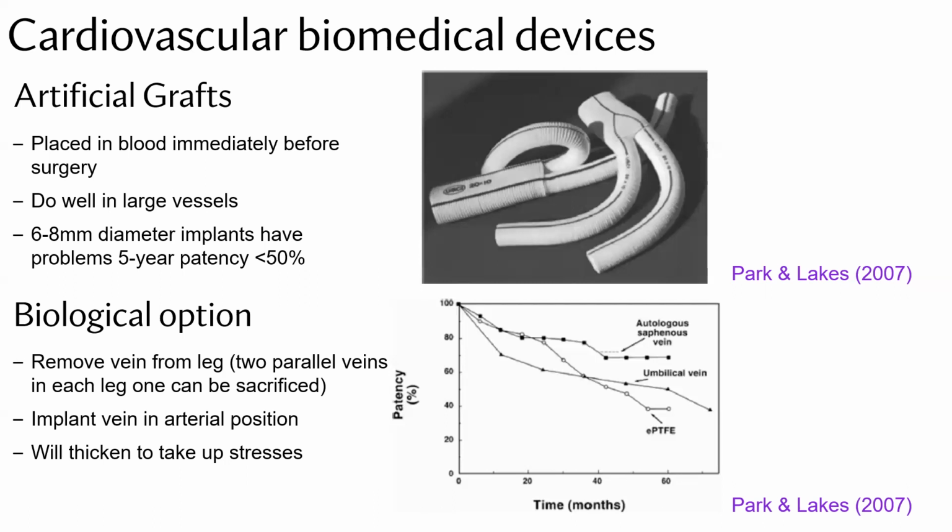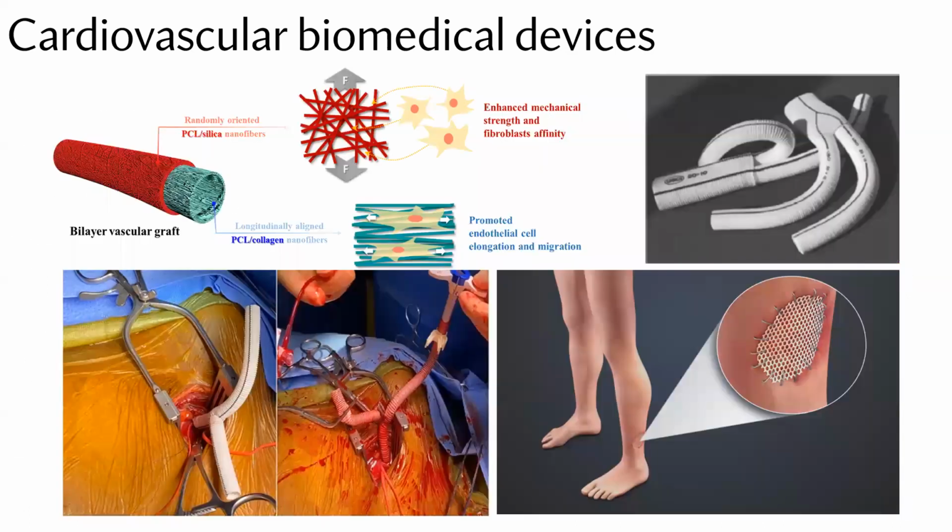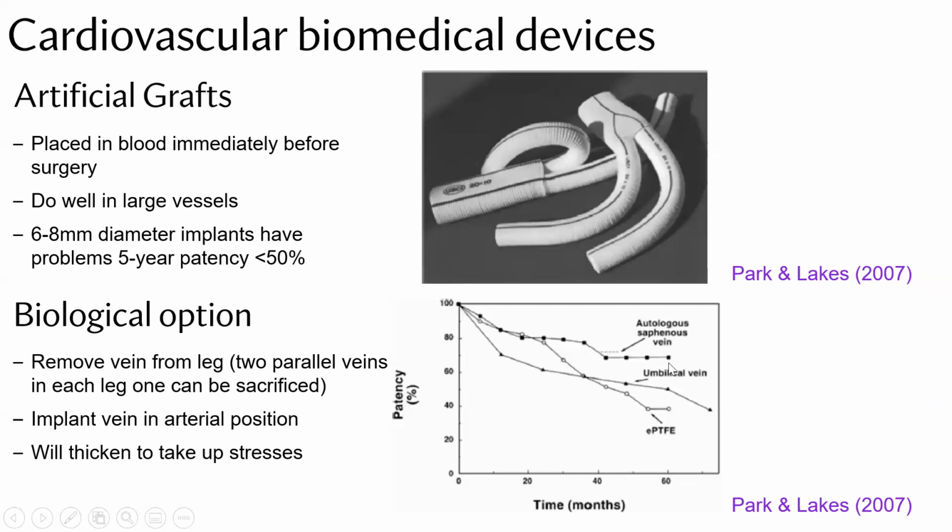Usually it's around 5 years. So the patency, as you can see here, the graph shows about majority of them really after a matter of 5 years are no longer useful. Some do a little bit better. Some are a little bit worse. But again, typically around the 5 to 6 year mark, they have to then change them. But by that time, we're hoping that regeneration and remodeling has already gone through its course of action.